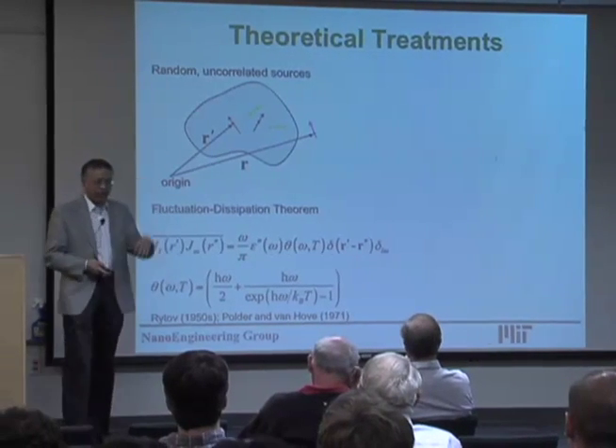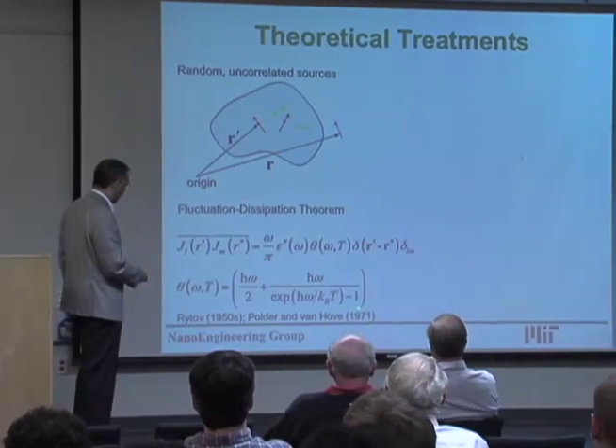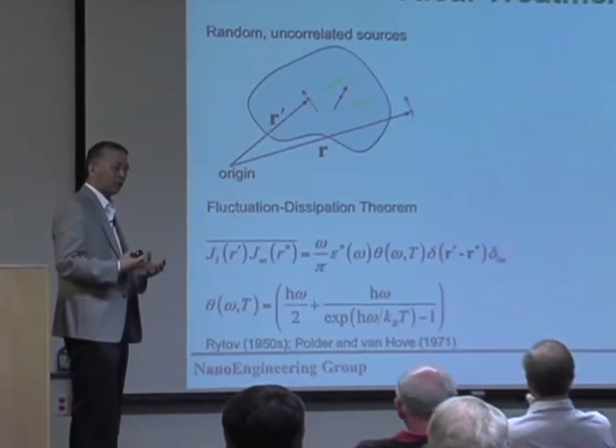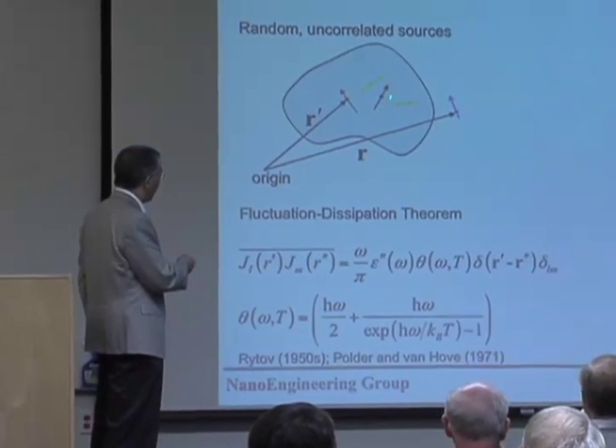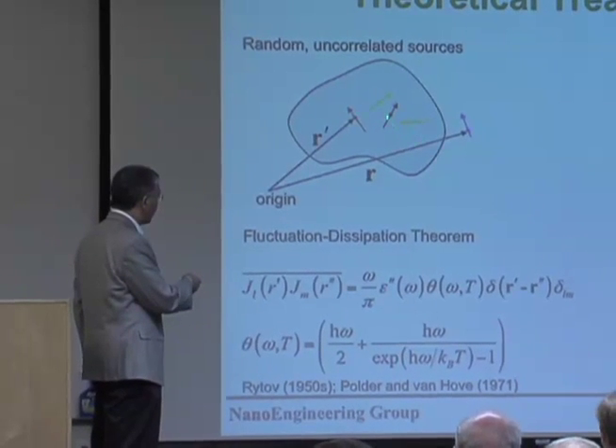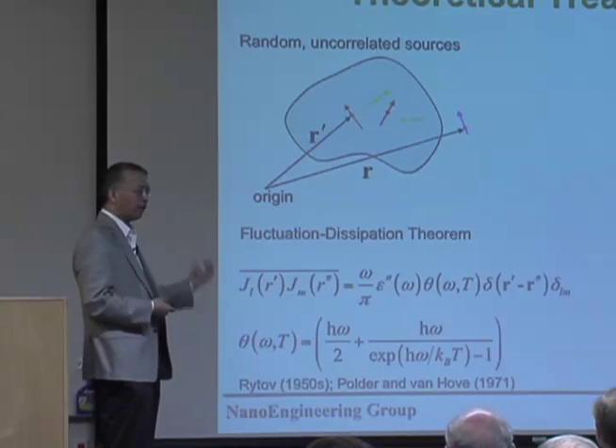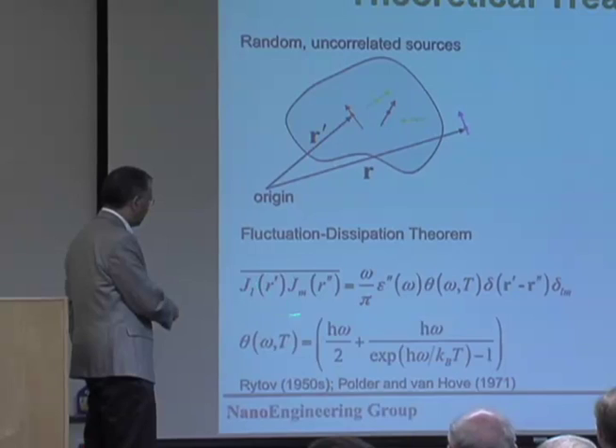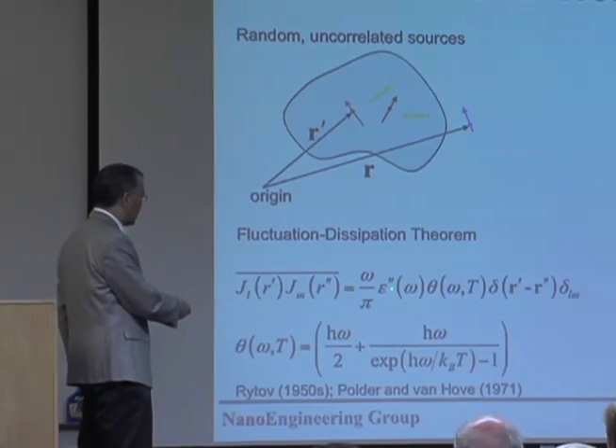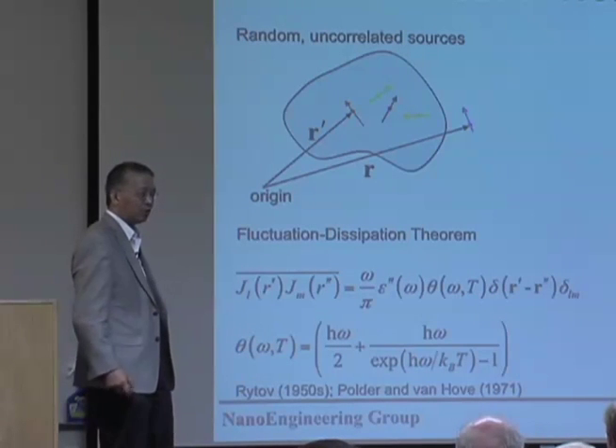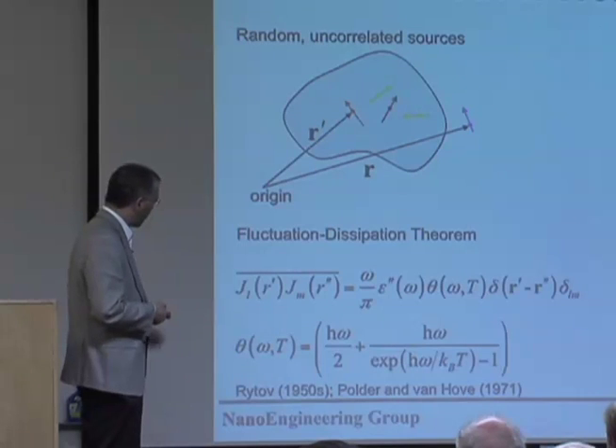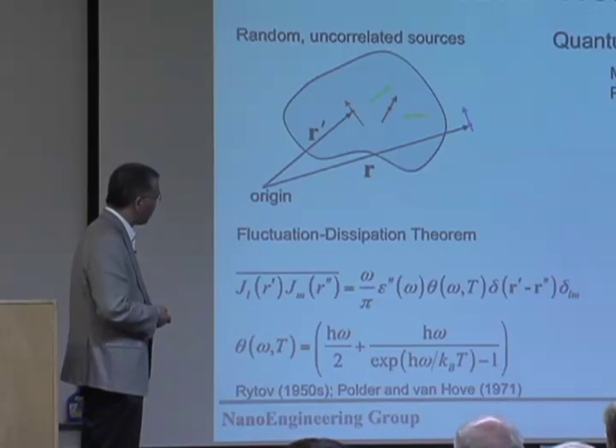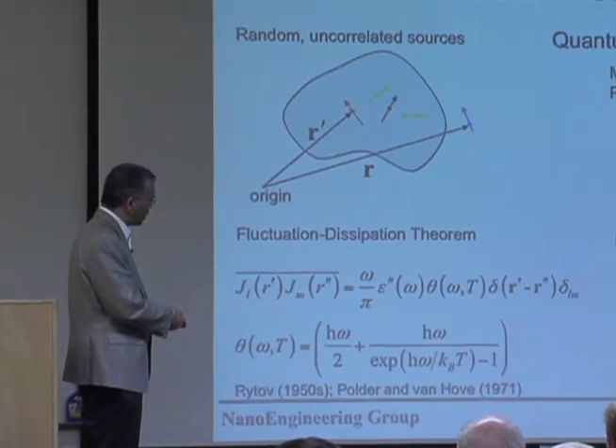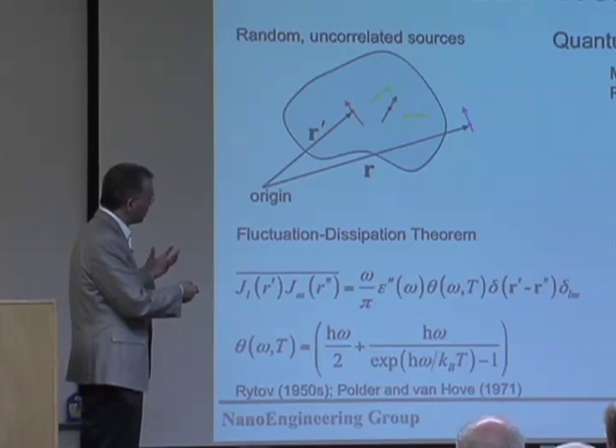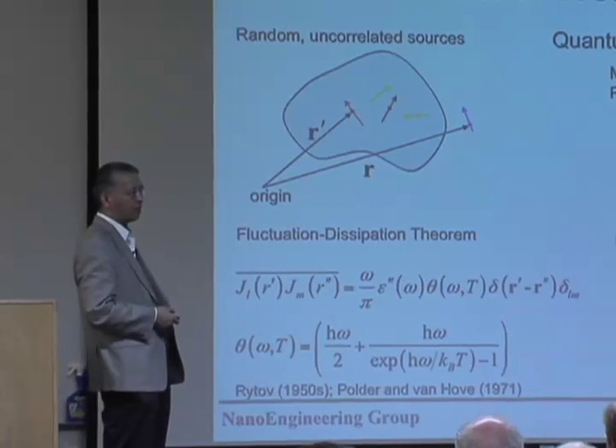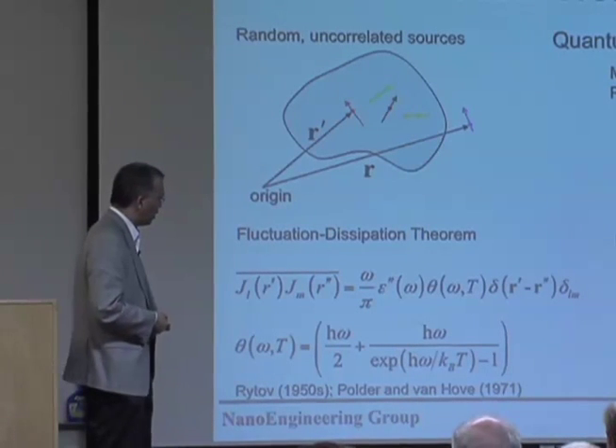So how do you do this calculation? It turns out the theory is there. This was established in the 1970s, basically using fluctuating electrodynamics. We think about a source here, you use Green's function, and calculate, if I have a fluctuating current, what's the electromagnetic field generated. And this fluctuating current is related to the imaginary part of the dielectric constant and related to the Bose-Einstein distribution. So with that, you connect with local temperature. And so basically, it's an electromagnetic wave calculation. There was an alternative explanation by John Pendry, who basically says this is quantum transport, and asks what's the maximum energy per channel. So it has a limit on the maximum heat transfer.